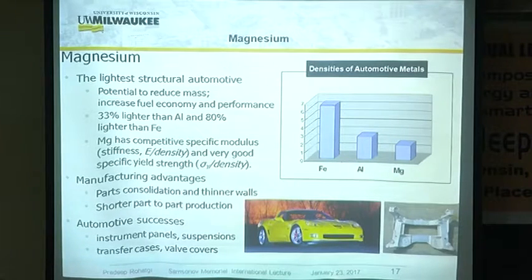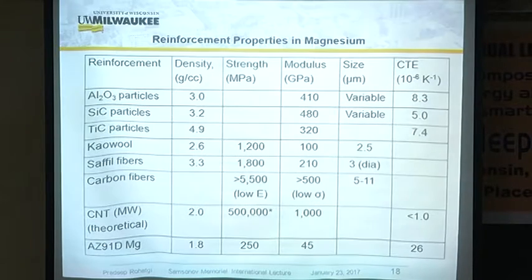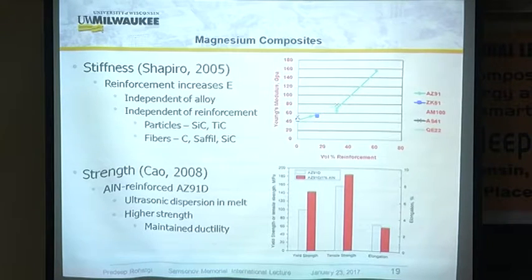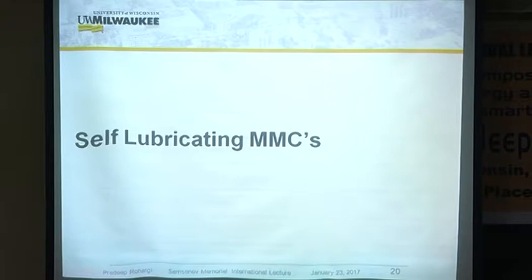I could go on. I did talk about magnesium, that is the new buzzword in which everybody is getting on because it is even lighter. This is the weight of iron, weight of aluminum and magnesium. So there's a lot of activity in magnesium matrix composites because magnesium has a low modulus. And if you put carbon fibers or carbon nanotubes or graphene, you could make magnesium much stronger and much stiffer, and it is very light. So this is the new game, and we are working on this ourselves. And as you add particles or fibers to magnesium, they become much stronger.